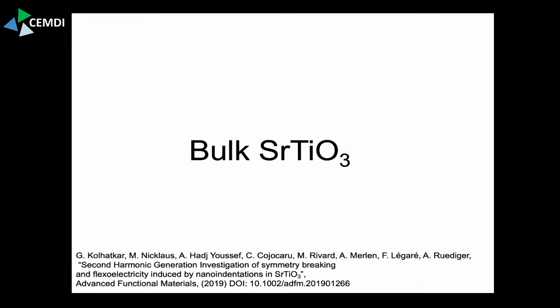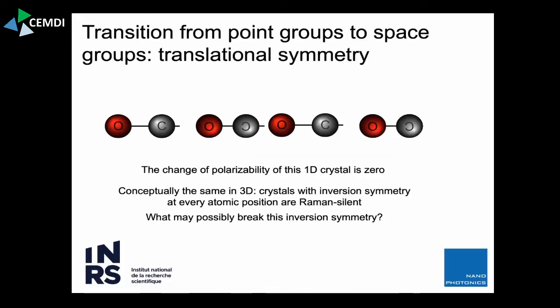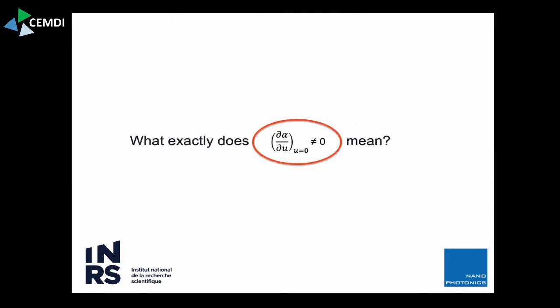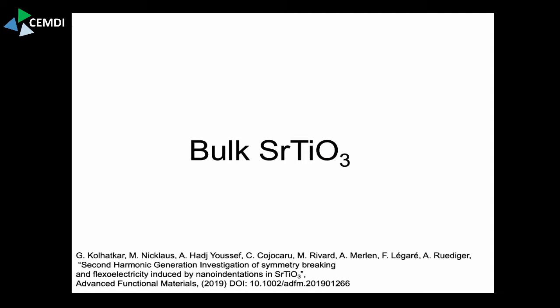Sorry, I was a bit quick here for myself. There is a way you can generalize what kind of symmetry you need. The symmetry that guarantees a crystal doesn't have any Raman signature is this: you put yourself on any position, on any atom or ion in the crystal, and if you have a perfect inversion symmetry for every location of every atom in the unit cell, then it's for sure Raman silent. So strontium titanate is such a case. Perovskite, cubic, and nothing goes on.